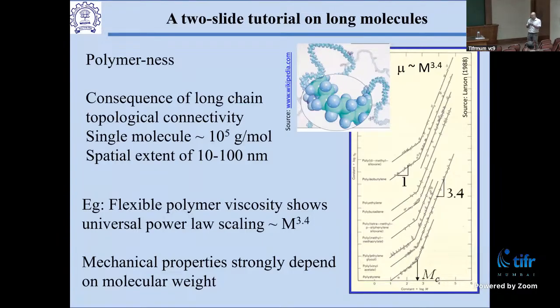So each polymer, depending on the detailed molecular structure of the polymer, has a certain degree of stiffness, and that stiffness determines the length beyond which polymers can start to entangle with each other. There is something called a persistence length, which tells you that if I look along the bond, how long does the bond orientation persist in space? And where do you lose the correlation between bond directions? So that gives you the persistence length. When you go beyond that, at some point the polymers get long enough and flexible enough that they can start entangling with each other.